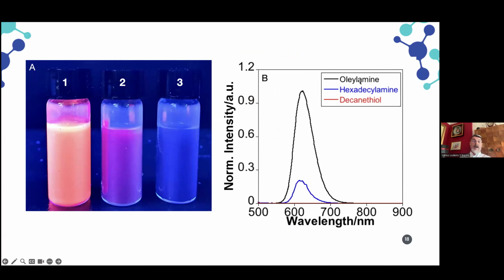If we use oleylamine, the oleylamine produces the red color solution and the emission has the highest intensity. If we use hexadecylamine, so we increase the length of the chains, we produce a very low emissive material. But for example, if we use decanethiol, in which we introduce a sulfur atom, we quench the emission completely, and that is the red line, and it is the blue solution that is completely plain.